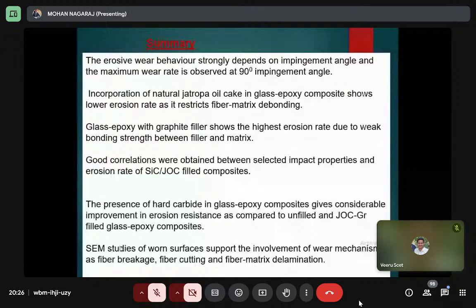Here, silicon carbide and oil cake filled composites: the presence of hard carbide in the glass epoxy composite gives a considerable improvement in erosion resistance compared to the unfilled, JOC and graphite filled composites. The images support the evidence of the wear mechanisms observed.